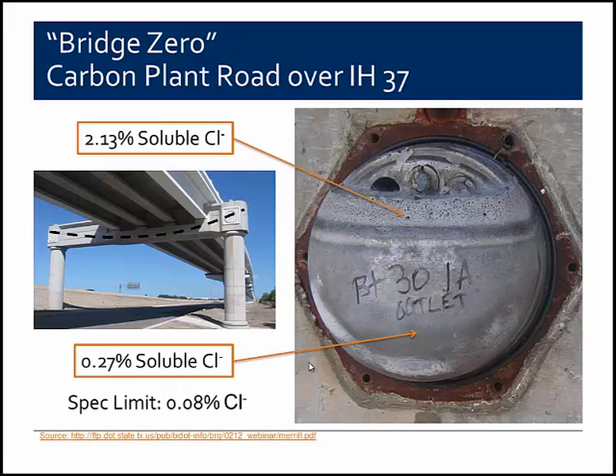So this is what would be called bridge 0. This was the first bridge to actually determine that the chloride was contaminating the grout, Bridge Zero on IH 37 in the Gulf Coast region of Texas. It's a straddle cap, as I mentioned earlier in the program. You can see the slide on the left shows a straddle cap, and that black dash line shows the approximate location of the 5 tendons in that straddle cap. And on the right is a close-up of one of the tendons with the anchor cap removed.